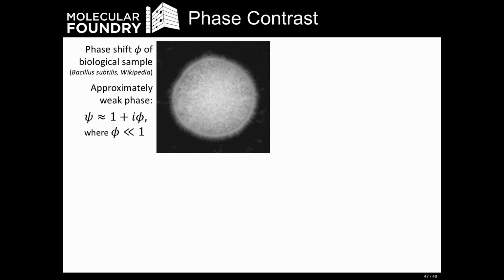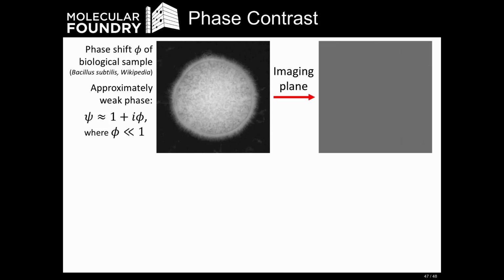The weak phase image just means it's equal to a carrier wave of one, plus the sample potential that I plotted here multiplied by the imaginary constant, where the sample potential is very, very small. In this case, about 0.1 rads, so quite small with respect to the carrier wave. So if I were to stick this in my microscope, a light microscope or an electron microscope, and take a picture of it, this is what I would see. Pretty exciting, eh? The problem with imaging a weak phase object is that when you're in focus, you see no